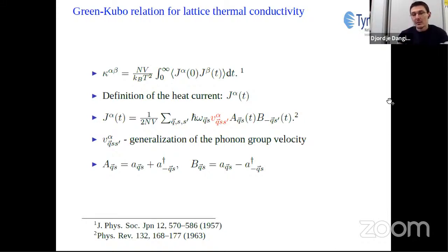We use the definition of the heat current shown here. People who are calculating lattice thermal conductivity from first principles will notice that this definition is different from the more commonly used Peierls one, which defines heat current through the phonon population operator. But one can show that the Peierls definition of the heat current is an approximation of this expression.